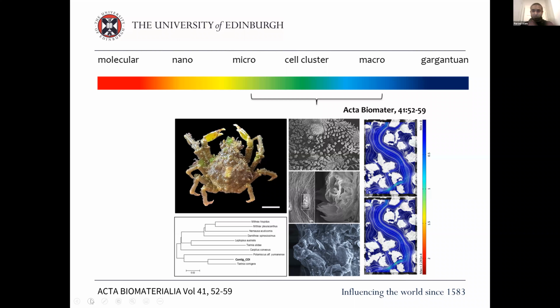So what's going on with these guys? We basically cleaned it up a bit, removed the macroalgae, and we did some SEM, and we found that there were these flowery haystack type structures growing out of the carapace. And if we did some CFD simulations on the surface of those, as you can see on the right-hand side, what we found is that there are these stagnation points that arise on the surface of the carapace. Now, our SEM also showed us that there are diatoms attached to these haystacks, let's call them. So what we understood then was that these stagnation points are basically holding diatoms and potentially other EPS secreting microorganisms. EPS means extracellular polymeric substances, and they are often in microorganisms very sticky. They are the things that cause biofouling.